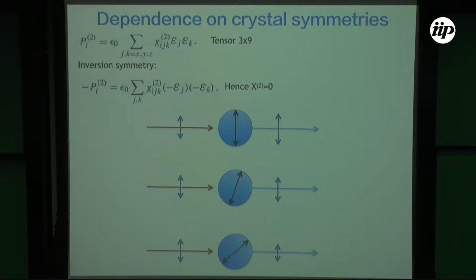And there are some interesting properties of the second harmonic generation. So basically, the second order polarization that's going to be created in your material due to the incident electric field depends on this chi2, okay? And this chi2, in fact, is a tensor, okay? It's a 3×9 matrix, and it depends on the crystal symmetries of your material, okay? For example, if you have inversion symmetry, okay? So it means if your crystal has inversion symmetry, if you apply an electric field, you change plus here to minus here, so applying an electric field in the opposite direction.